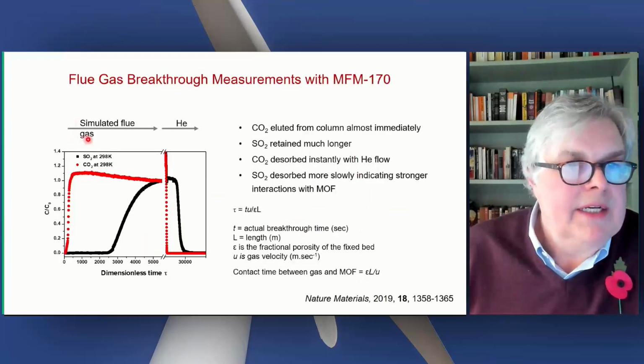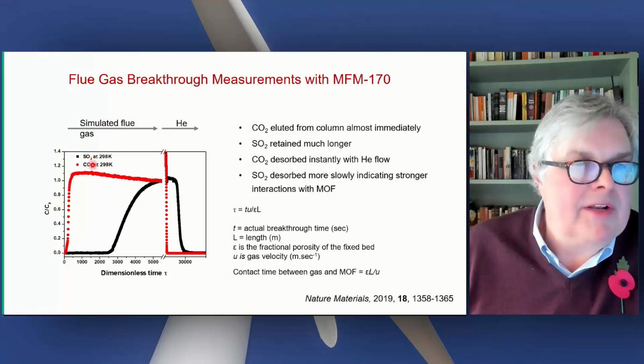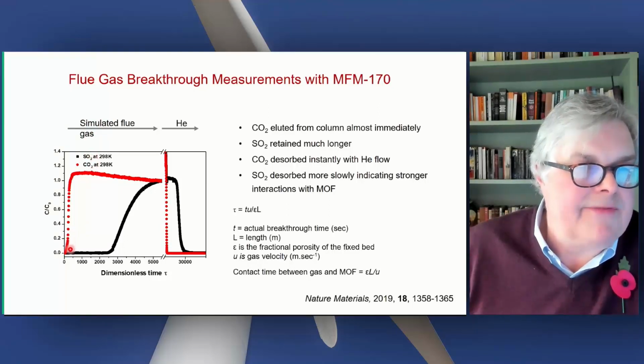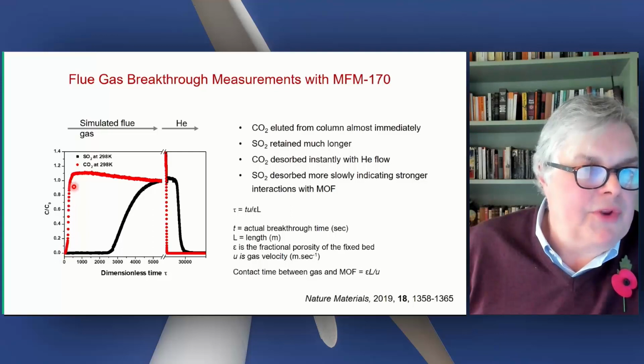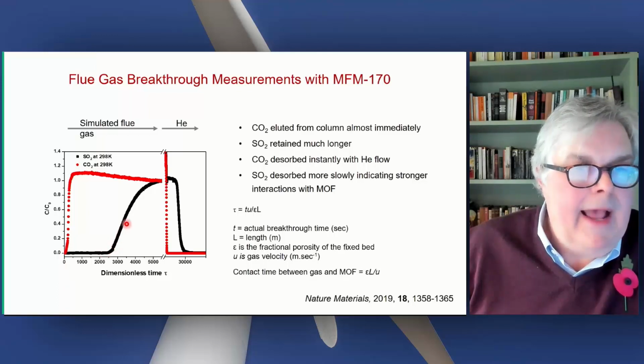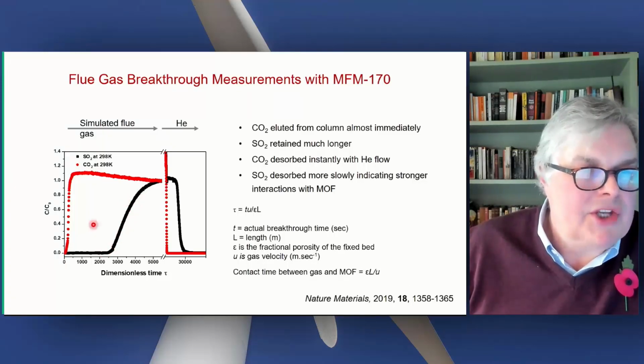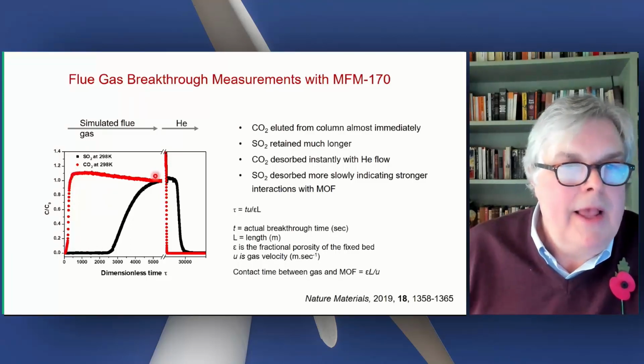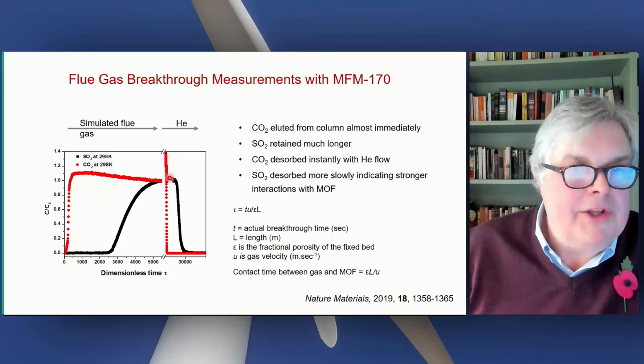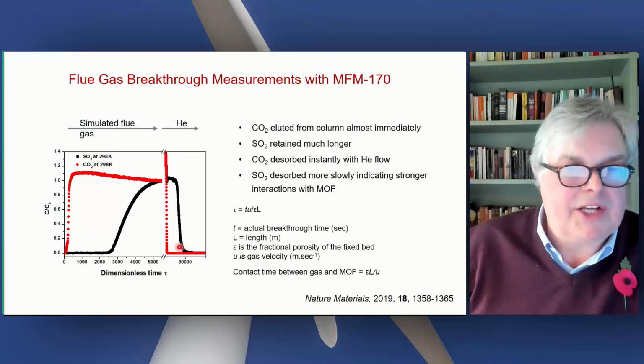And here is a straight breakthrough experiment of SO2 and CO2 illustrated in a different way. CO2 comes through the column very quickly. SO2 is retained because it fits in the pores more effectively and then comes out later. So during this period, you're basically purifying the CO2 and what's coming out is pure CO2. You then introduce a flow of helium, and you can see the CO2 comes out very quickly, and then the SO2 is flushed out of the system.